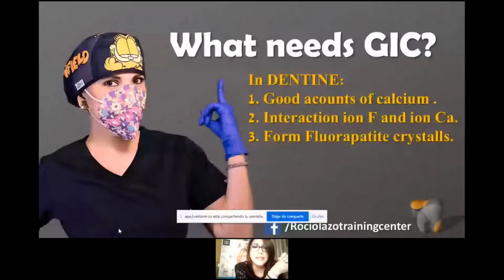What happens with resin? Because you said, okay, maybe glass ionomers are not a good option. And what happens with resins? The problem with resins and a bad adhesion in the affected dentin is because we have present the matrix metalloproteinases. The metalloproteinases are sleeping in the dentin. And when you are using the orthophosphoric acid, you are going to wake up again the matrix metalloproteinases. And these metalloproteinases will be eating this adhesive, so you're not going to have good adhesion.